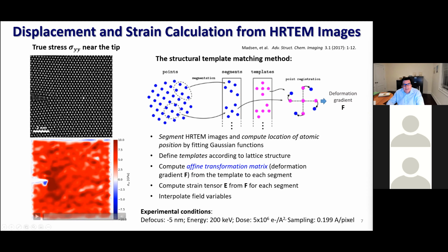There are many details here, like the degree of defocusing and the magnification and the electron dose that is used to achieve very high resolution. But if you read this paper, you will find a lot of interesting studies in that respect. The key here is that you can fit Gaussian functions in each spot and get sub-pixel resolution, which brings a good determination of the displacements.